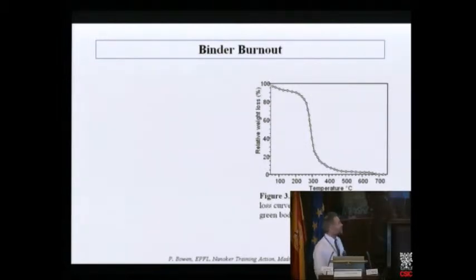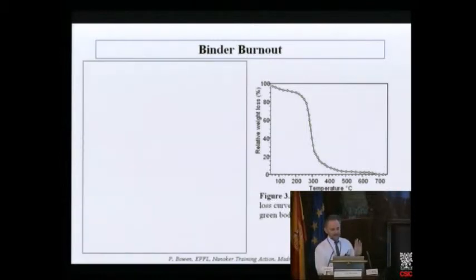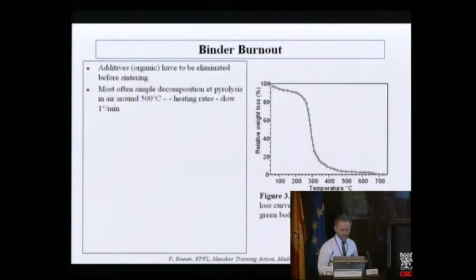So, binder burnout. Normally we follow the weight loss as a function of temperature. This is really very important. Normally it's just a simple heating at a slow rate. So we have to give the organics enough time to come out. We heat up, normally up to about 500, 600 degrees centigrade. We have a little bit of water, excess solvent. This is typical for a slip with polyacrylic acids, where we only have one component. This comes out at about 250 degrees centigrade.